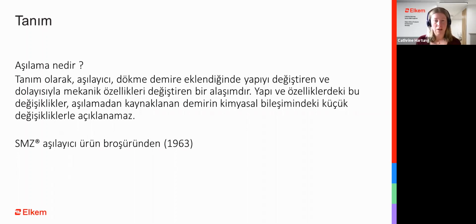So the difference with a good inoculant is that you can use so little that you do not change the composition of the iron itself. If you have to use a considerable amount of inoculant, then you will also experience a change in the chemical composition, because normally the inoculants that are used today are based on ferrosilicon, and silicon will change the carbon equivalent of the iron itself. But if you have an inoculant that is highly effective, the addition is so little that it should not have an effect on the chemical composition itself.